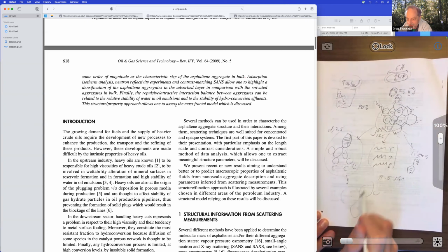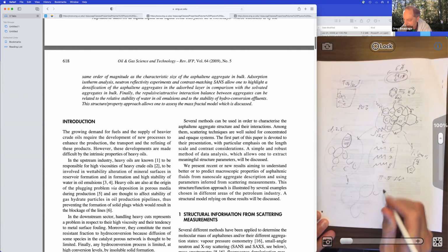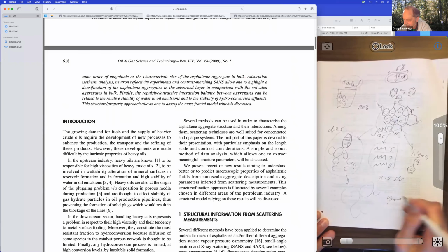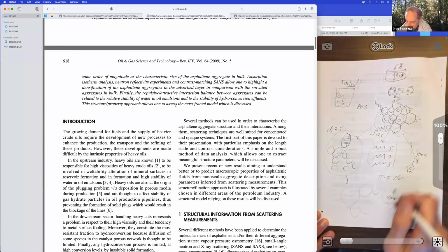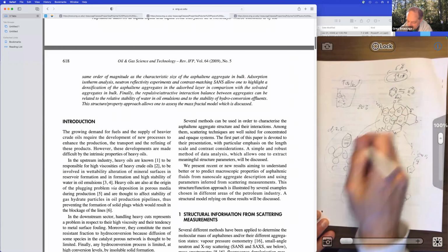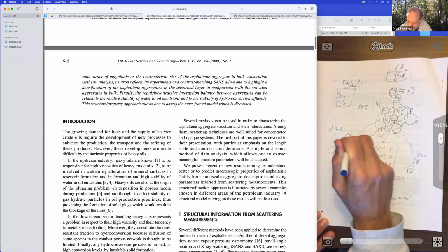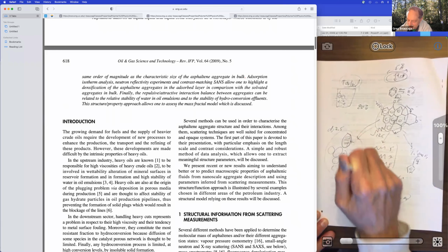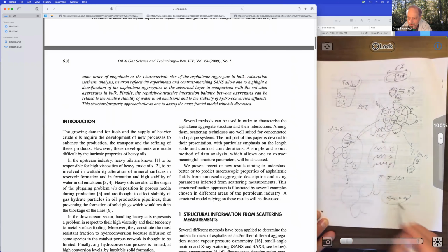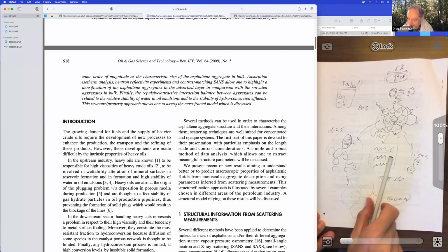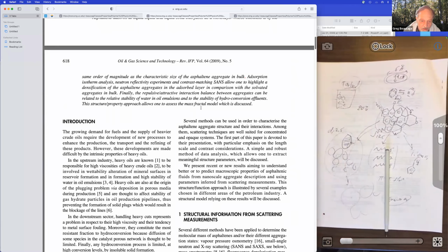It's these clusters and networks that form that's a problem, on the order of like 10 micron to meters, to a large size. But it's built on this hierarchy going back to these stacks. So if you can prevent the stacking, you won't get the primary particles, and you won't get the aggregation, you won't get the agglomeration, you won't get the networks, and you won't get the clogged pipe. That's the idea of the asphaltene studies mostly.